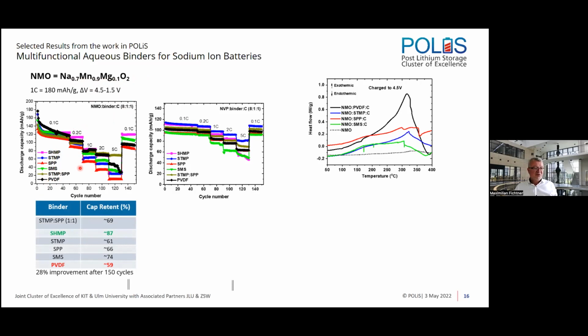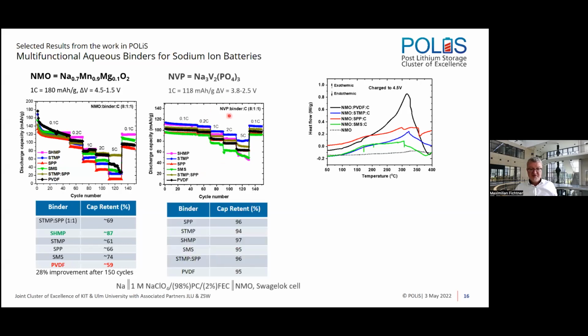And you basically see that there is a much better performance after some cycling when the inorganic binder is used. You see here, this is for NVP. The black line is for the PVDF, and the others here are inorganic binders. This is a metaphosphate here. Sodium trimetaphosphate is performing much better, and you see a considerable difference here. Also, the safety is better.